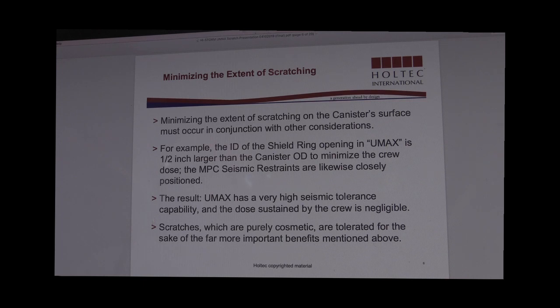And the shield ring has a specific purpose: to limit the radiation dose to the crew during field operations and the MPC download event. So for that shield ring to be most effective, the clearance gap between the canister OD and the shield ring is kept to a minimum to the extent practical. In this case, the diametral clearance is approximately a half inch between the ID of the shield ring and the OD of the canister. And that enables us to effectively reduce the dose in the field during download operations.